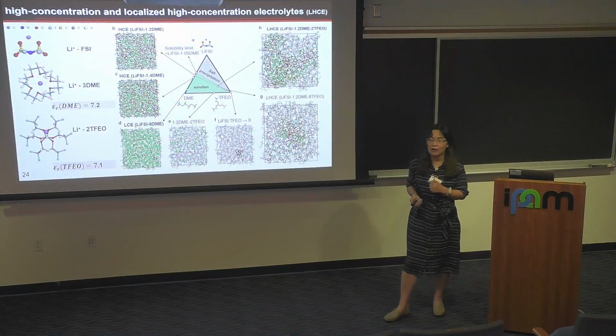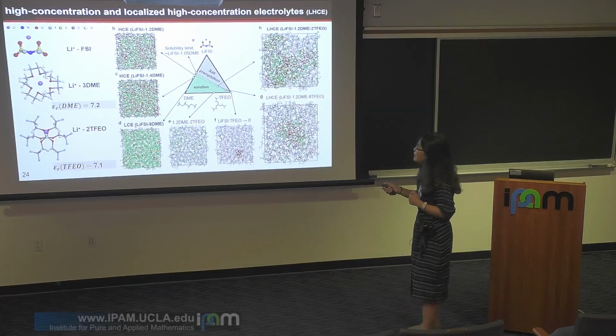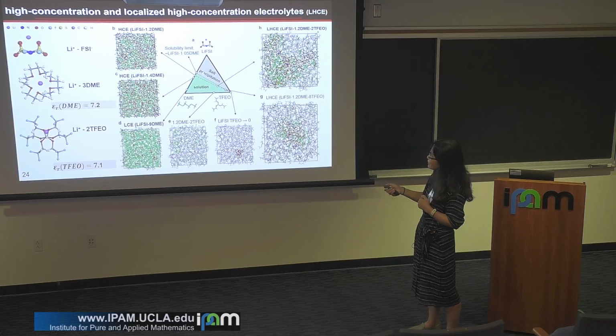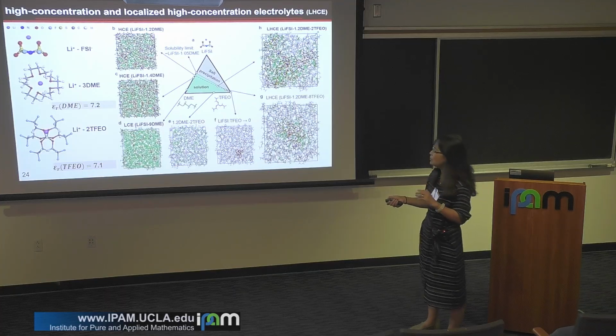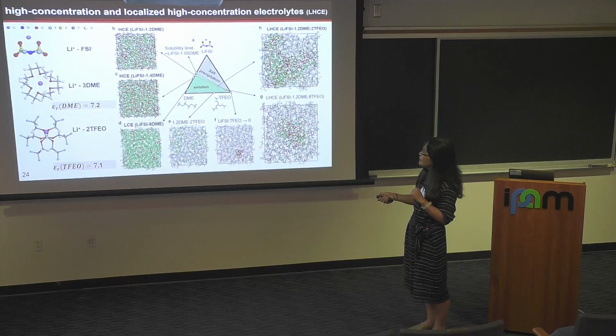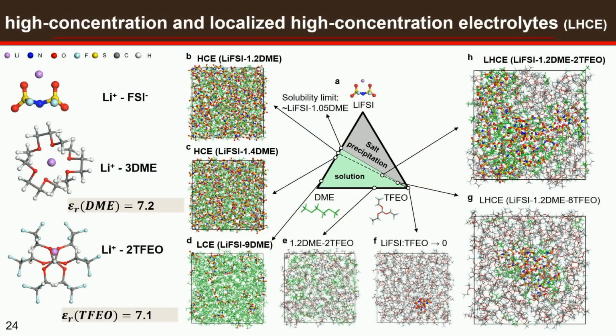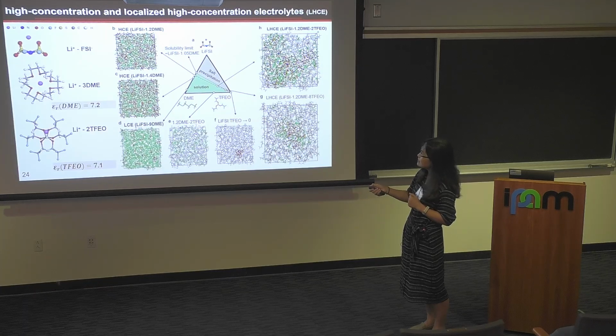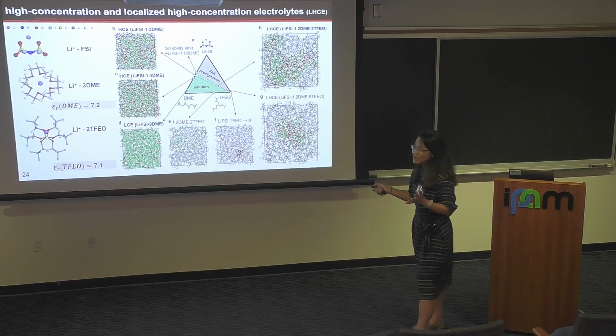So let me move to a little bit more complex electrolytes, right? The previous electrolytes were 1 molar, so about here, and this is like a 1 to 10 ratio of lithium ion to solvent, right? If we increase the concentration up to here, 1 to 1.2, that's about a 1-to-1 ratio-ish of the salt and the solvents. Really, there are a lot of aggregates of the salt and the solvent, right? So that is the salt and that's solvent. And this molecule, I'm not a chemist, so I don't know the names, TFEO or something.